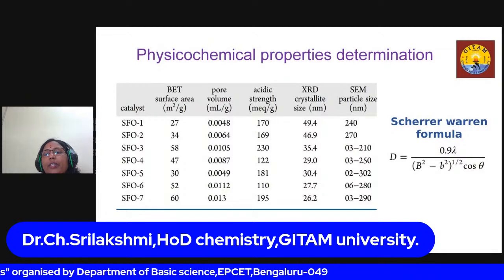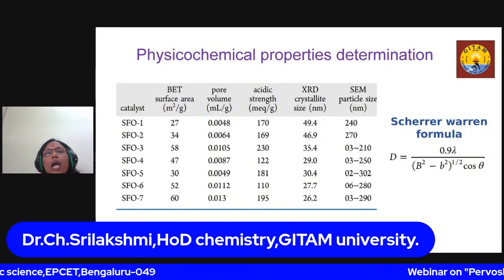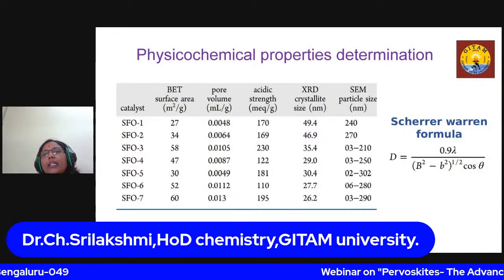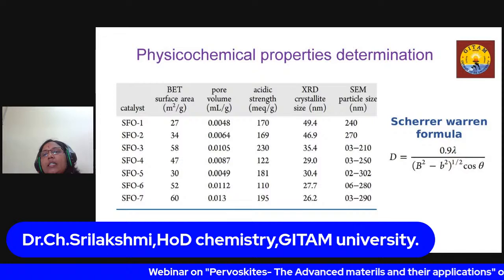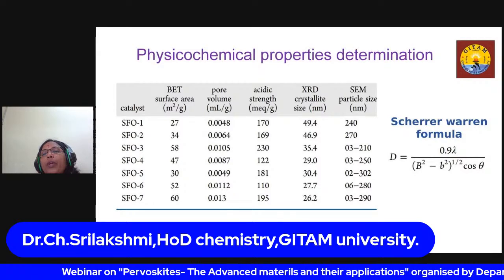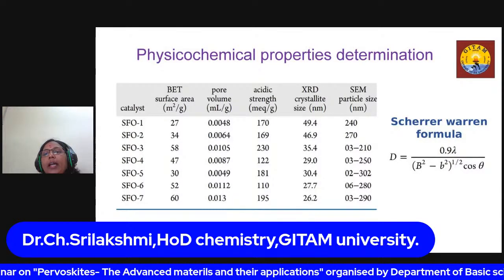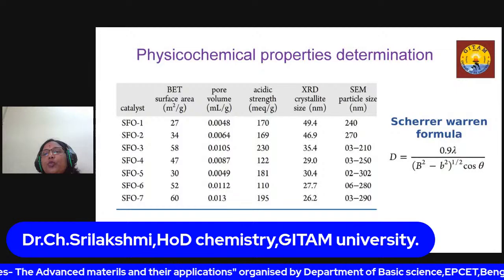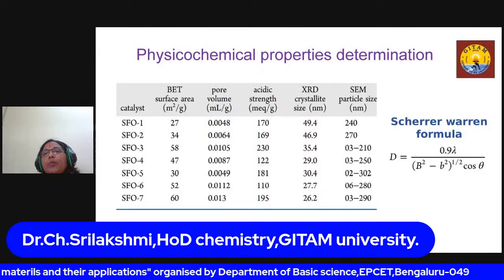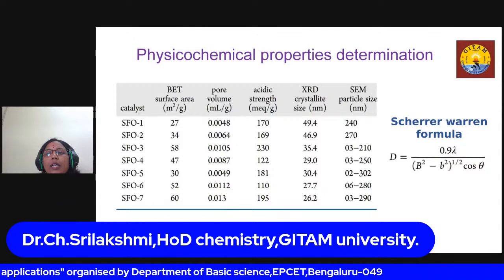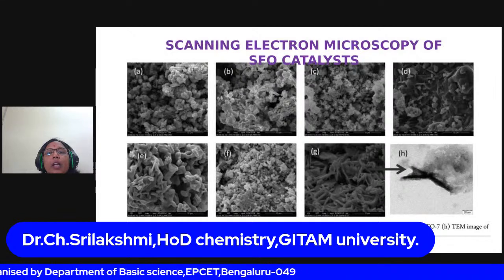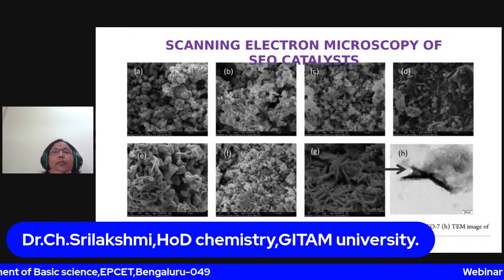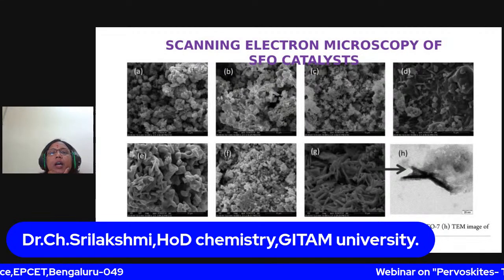This is the equation we use for the calculation of crystallite size using XRD, called the Scherrer equation. This is the wavelength of the X-ray, and these two B's are the full width at half maximum of the reference and the sample compounds. And these are the SEM images, as you can see.